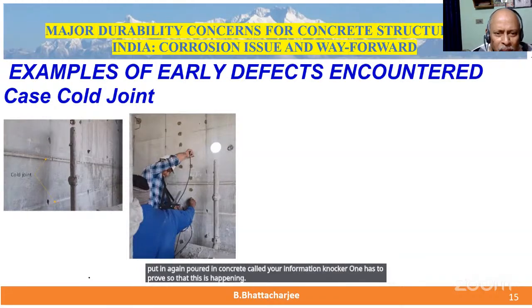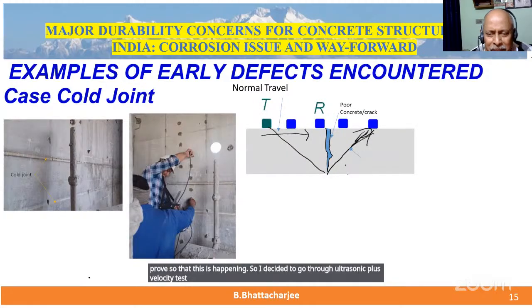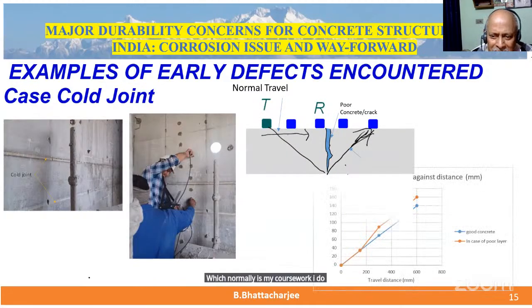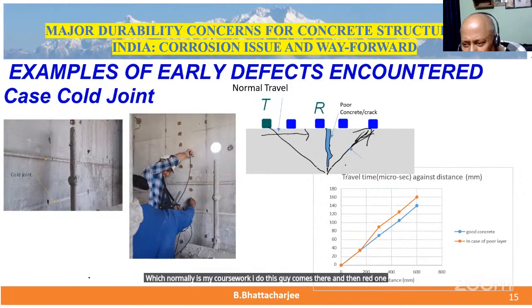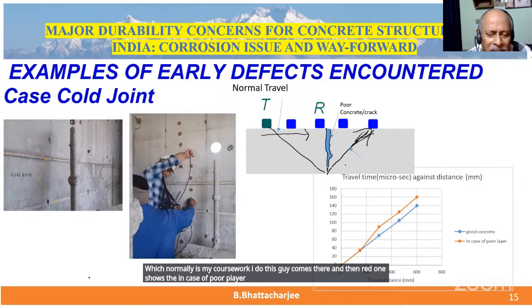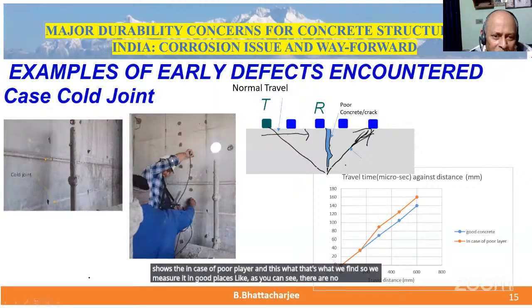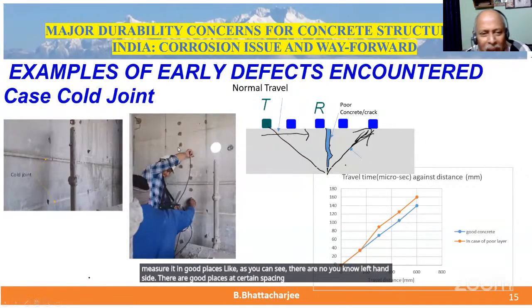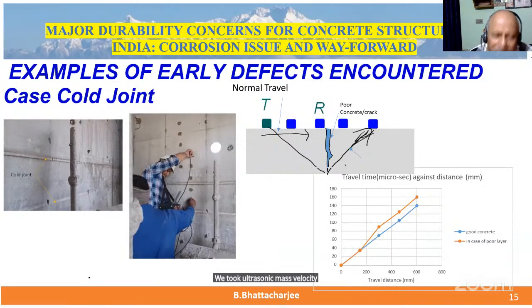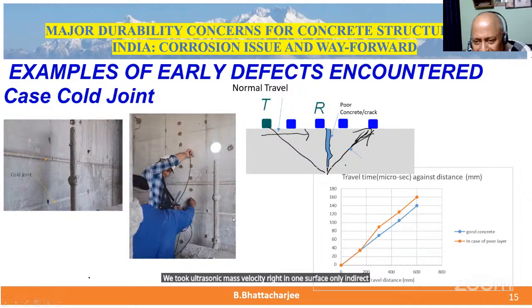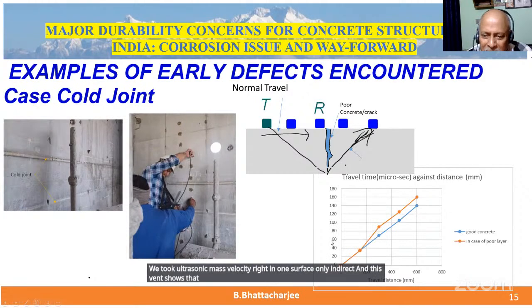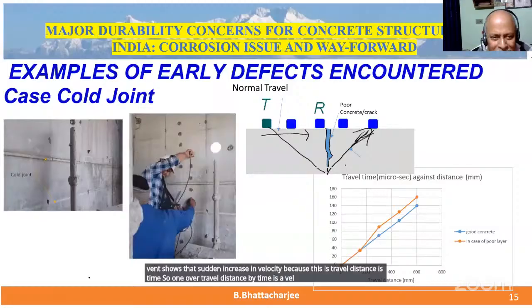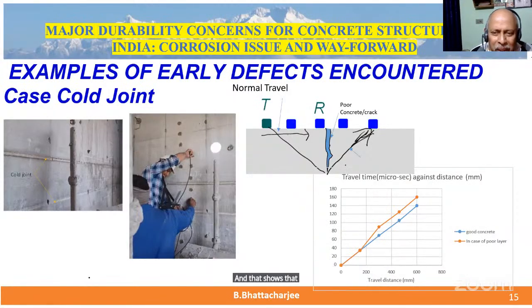So I decided to go through the ultrasonic pulse velocity test, which normally is my coursework. This diagram is there. And then the red one shows the case of a poor layer, and that's what we find. So we measured in good places, as you can see, left-hand side. There are good places at certain spacing. We took ultrasonic pulse velocity, right, on one surface only, indirect. And this bend shows a sudden change in velocity, because this is travel distance, this is time. So travel distance over time is velocity. So velocity reduced suddenly, and that shows that there was a problem. So we anyway suggested a repair scheme.